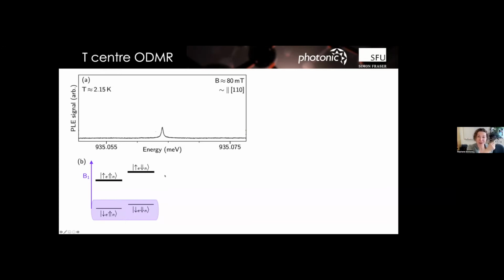So much so that if you raster a laser over top of it, you actually hyperpolarize more quickly than you get luminescence, right? So you actually only get a couple photons before everything hyperpolarizes in a spin way. So if you drive it across, the same sample that we saw on the previous slide, but you take a resonant laser and you drive over it rather than look at the total photoluminescence, you actually only get this one little center peak. And what you're getting here are the defects that actually have the same splitting in the ground state as the excited state, which means you don't hyperpolarize. So that's the only contribution that you see.